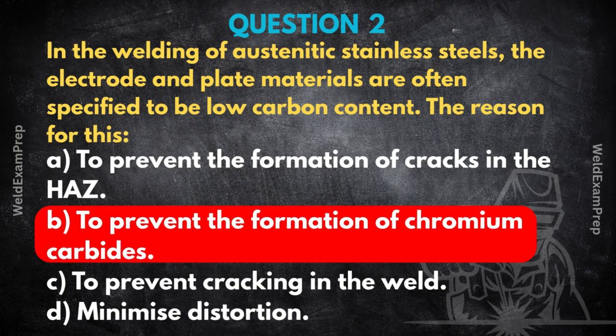Yes, and this is a really, really important concept in stainless steel metallurgy. It's all about corrosion resistance. You see, with austenitic stainless steels, if they have higher carbon content and they get heated during welding into a specific temperature range, roughly 450 to 850 Celsius. The sensitization range. Exactly, the sensitization range. The carbon atoms can move around, they migrate to the grain boundaries, and there they combine with chromium to form chromium carbides. Okay. Now, this process, sensitization, it depletes the areas right next to the grain boundaries of chromium.